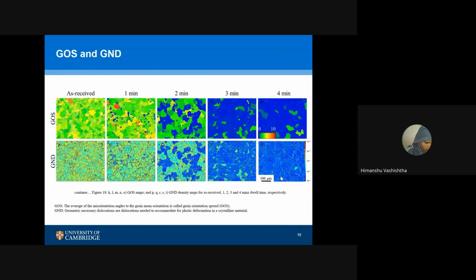In this experiment, we have calculated the dislocations, called GND, geometrically necessary dislocations. Before going to that, one thing is grain orientation spread, on a scale of 0 to 10, where 10 is on the higher side. Initially it's on the higher side, but when we heat it, it goes lower and lower, showing that the material is getting stress-free with heat treatment.